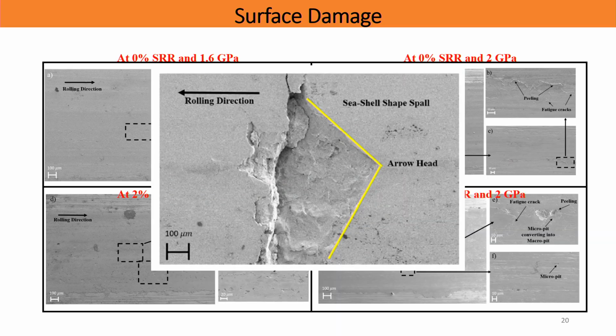What it tells you is that actually this ferrite is softer than perlite. So perlite is cracking up, but it is also squeezing the ferrite. So there now starts happening the crack generation at the boundary. You see, so can we have rails without ferrite? Right. One is this, to reduce this, because otherwise this is a serious thing. For we are trying to increase speeds also now.